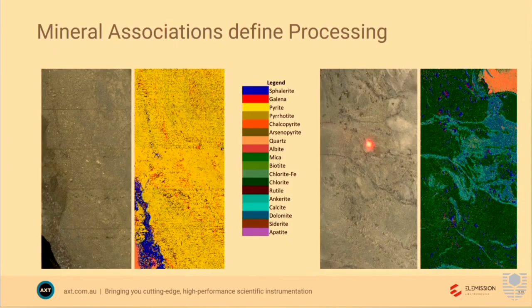This one here is, again, looking at sphalerite type of minerals, but from a mineral processing point of view, or even exploration geology. So these are the two digital photos. They both look a bit similar, very bland grey, but then you start doing the mineralogy. In this case, you've got the sphalerite that's associated with pyrite, but over in this one, you've got your sphalerite that's associated with micas, so mica and biotite. So they're both micas, but very different end applications for process mineralogy, as well as the exploration geologist to work out what they're associated with. So it's a very fast way of scanning core. It can analyse the sample, as long as the surface height is within 4 millimetres, you can zap it directly.